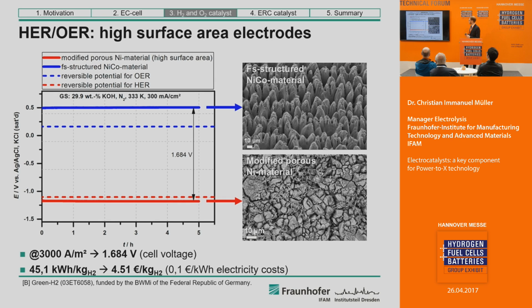Just to give you one example, we have developed different materials in different projects, and this is just an example of this. Shown here on the diagram on the left side is the potential of the electrodes versus the time. The dashed lines give you the reversible potential for the oxygen evolution in the case of the blue dashed line, and the red dashed line represents the reversible potential for the hydrogen evolution reaction. We have developed electrodes that are very highly efficient and also have very long-term stability. For the oxygen evolution reaction, we have used these femtostructured materials based on a nickel-cobalt alloy. You see these cone structures here, which have a very high surface area and are very active. Also, we have developed these roughened nickel materials, which also have a very high efficiency.